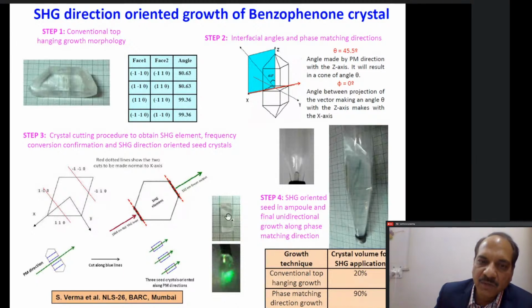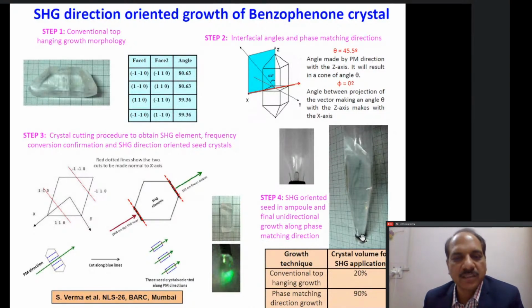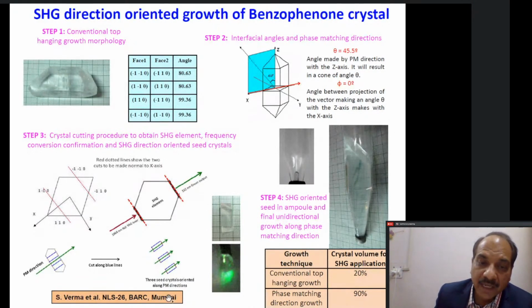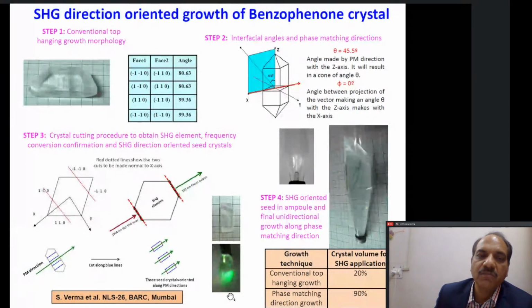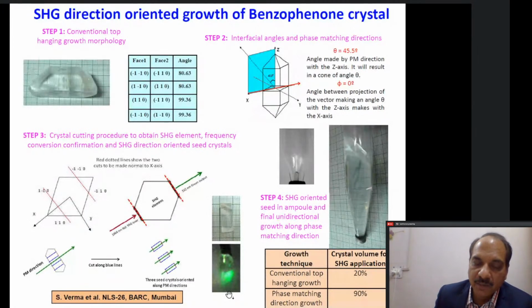Each of these elements, this is the element which we obtained from this crystal, which we used as a seed finally. This was tested before we put it inside the furnace for crystal growth, because we wanted to make doubly sure that the direction with which we have cut the crystal, which we are assuming to be a phase matching direction, actually is a phase matching direction or not. So before putting it inside the growth chamber, we did this trial experiment, and we were sure now that the axis of this seed is the phase matching direction.